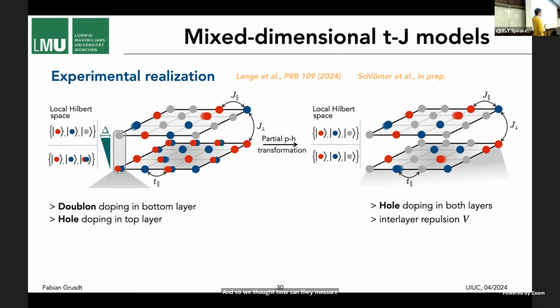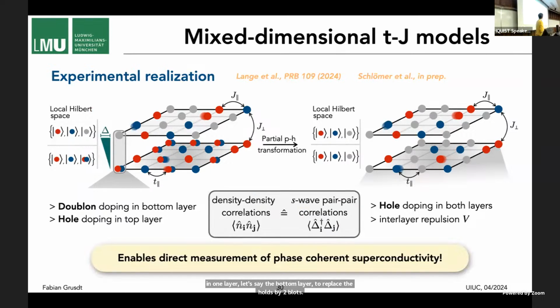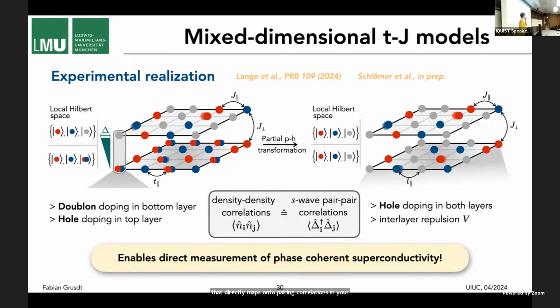And we proposed to realize exactly this type of bilayer using the mixed-D trick, and actually play one more trick, which is to replace the holes by doublons in one layer, let's say the bottom layer. At first, it doesn't seem to do much, but it turns out that if you measure density correlations in this doublon plus hole doped system, that directly maps onto pairing correlations in your purely hole doped system by an exact mathematical mapping. And this is great, because it means cold atoms are now in a position, at the current temperatures they're at, to directly measure phase coherence and then measure such a superconductor in the lab, without any further tricks they need to play.